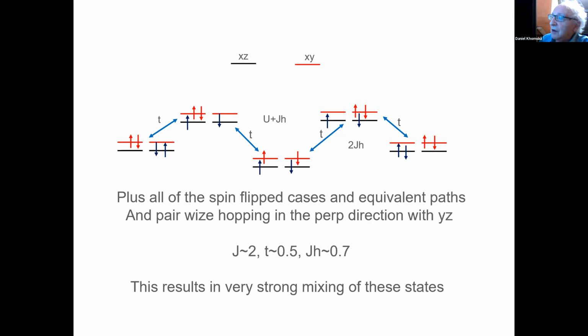Would it depend on the material, whether you are dealing with iron selenide or 122 or 1111, or would it be more or less the same in the whole class of these? I think these parameters are so sensitive that I can imagine changes, but the qualitative physics would be the same. I think this would happen all over, but by changing parameters, you can either go into the nematic phases, or you could go into a magnetically ordered phase, or a spin density wave phase, and maybe even a superconducting phase.